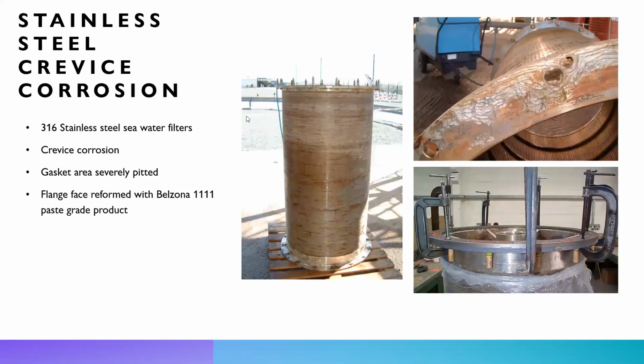So going into some examples, like I said before, 316 is known as the marine grade, but you can still have issues, especially dealing with seawater, high velocities, and increased temperatures. You're going to have corrosion, erosion. So this is one where there was crevice corrosion at the gasket. Instead of having to buy a new filter here and have the same issue over time, what they opted to go with was a flange face forming with a non-metallic Belzona 1111. So basically we prepped the flange and fabricated a former to go over the top, and we made a new flange face out of Belzona 1111, which is resistant to salts and also takes away that pathway for the salts to get in that crevice and cause crevice corrosion with stainless steel.